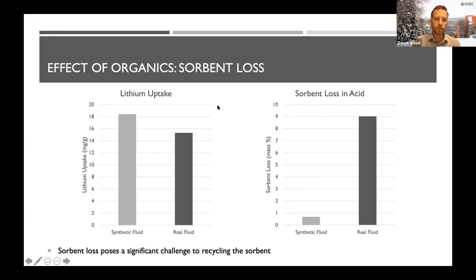Some other data as well, lithium uptake. Now here we're going to compare the real brine, that's the real fluid that we've been talking about all along with the 40 parts per million, with the synthetic fluid. And the synthetic fluid is just a brine made up in the lab. It has sodium and chloride at the same 180,000 parts per million total salinity. And we just spike it with the 40 parts per million lithium. So it's super simple, doesn't have any organics, none of that kind of stuff. It's just the same salinity and it has the same concentration of lithium. The real fluid is much more complex, right? It has a lot of ions in it, a lot of organic compounds. And what we see here is there's a difference in lithium uptake. So we get about 18 in the synthetic fluid, less in the real fluid, but not a dramatic loss.